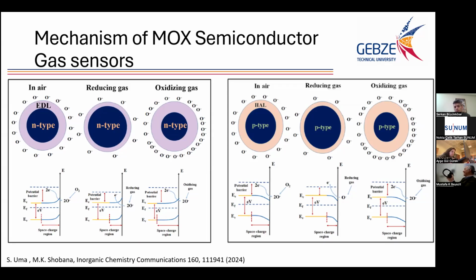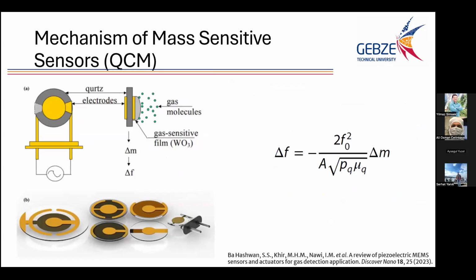for the chemiresistive sensors. If you look at the mechanism of the mass sensitive sensors, here I'm talking about the QCM, which is the quartz crystal microbalance. It is actually a piezoelectric material sandwiched between two electrodes. And if you apply a time varying voltage to these electrodes, you can vibrate the QCM at its resonance frequency. This QCM technology is very well established, and it's already commercially used mostly for thickness monitoring. I'm sure you are all familiar with the thickness monitoring in vacuum chambers in the laboratory, and you see there's a formula which gives the frequency shift according to the mass load on top of the surface.